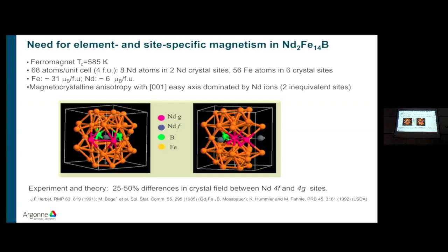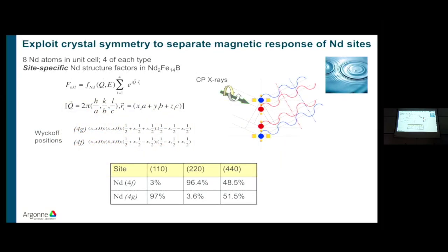So if you look at this, I made a plot where the neodymium G site is at the center here. You see this site has 1 boron atom and 3 neodymium neighbors. The other neodymium type of atom, the F site, has 2 borons and 2 irons, 2 borons and 2 neodymium atoms. So they have different neighbors. That means the crystal fields are different. And you would expect that perhaps each one of these neodymiums will contribute differently to the magnetocrystalline anisotropy or the coercivity of this material. So we want to separate not just the elements, but we want to separate also the sites. So how do we do that?